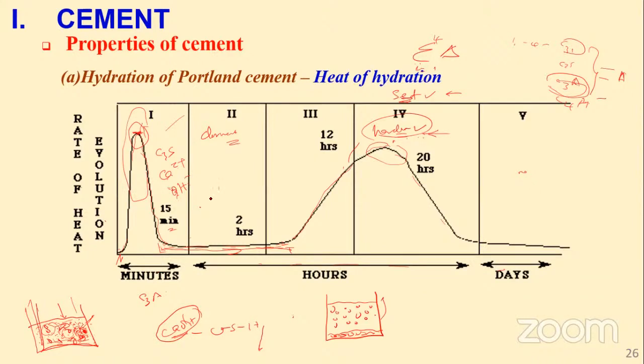Again, if we are mixing our concrete or cement paste in an area where the ambient temperature, the surrounding temperature, is high, then the heat of hydration will be high. Then the type of cement. As we are going to see the different types of cement, there are those that harden quickly. We say rapid hardening. That means they have a high content of tricalcium aluminate and tricalcium silicate. So depending on the type of cement, the heat of hydration will also vary.